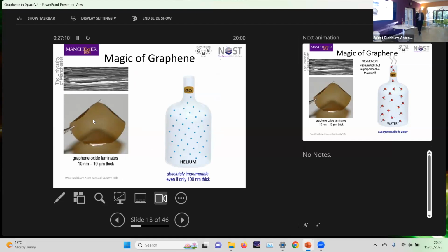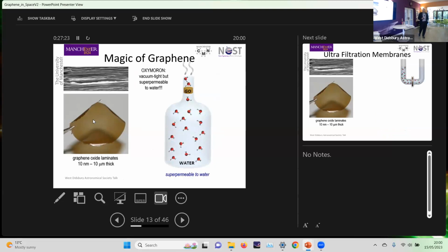if you take some of this graphene oxide, it won't let helium through at all. Helium's a very light atom. It should zip through it, but it doesn't. It won't go through. But if you replace that helium with water vapor, that goes through very, very easily. And the reason for that is that the channels are actually filled with water, essentially. So they have molecular water, which is bonded in there and stops anything else going through except water, because the water can replace the water molecules through the channel.